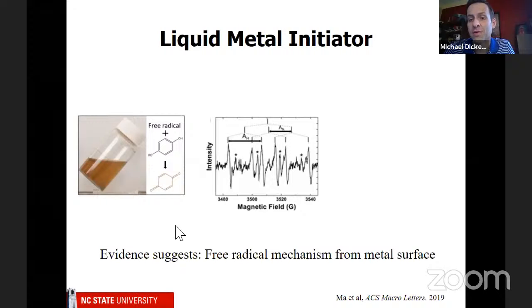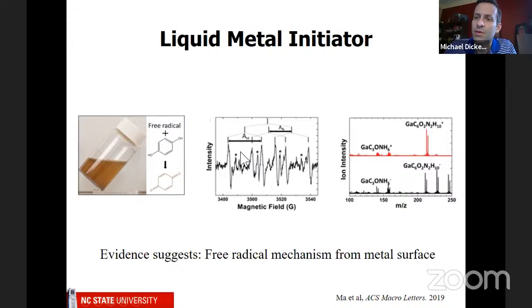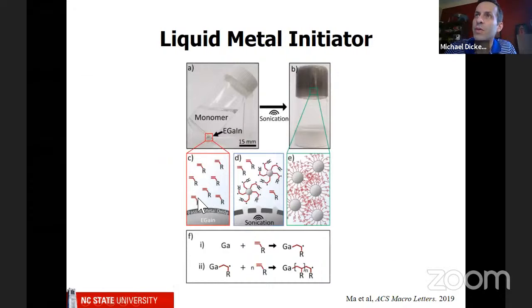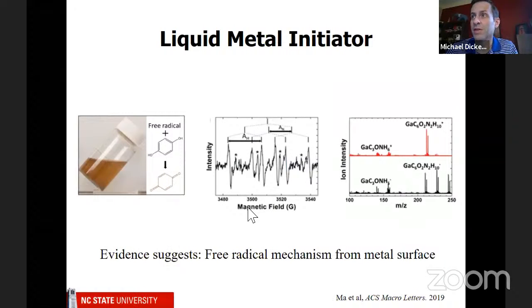You can also measure radicals using a special technique called electron paramagnetic resonance. It's called EPR. And I'm not an expert in it, but basically when you see peaks in this measurement, it tells you that there's radicals. So we've measured radicals kind of indirectly and directly. And then finally, we use this technique called time-of-flight SIMS, and I don't want to go into the details, but basically it allows you to identify chemical species that form. And we were really excited because we saw gallium directly connected to the monomer. So if I go back, we see that these chemical species are directly attached to the gallium. And so that suggests that the metal itself is initiating the polymerization.